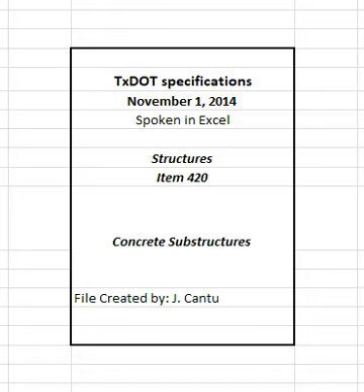Submerge the lower end of the tremie or pump hose in the concrete at all times. Use continuous placing operations until the work is complete. Design the concrete mix in accordance with item 421, hydraulic cement concrete, with a minimum cement content of 650 pounds per cubic yard for concrete to be placed under water. Include an anti-washout admixture in the mix design as necessary to produce a satisfactory finished product.